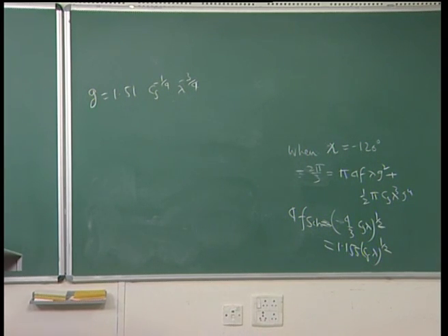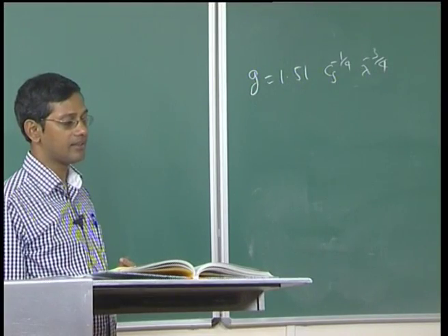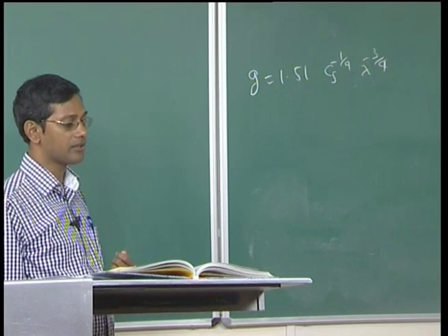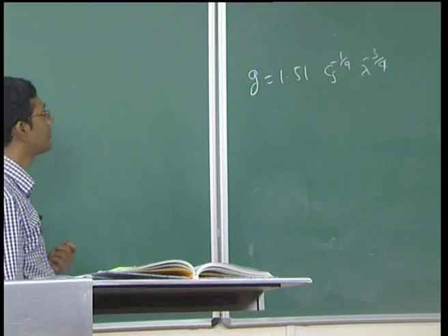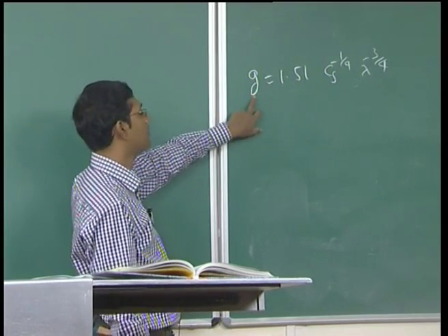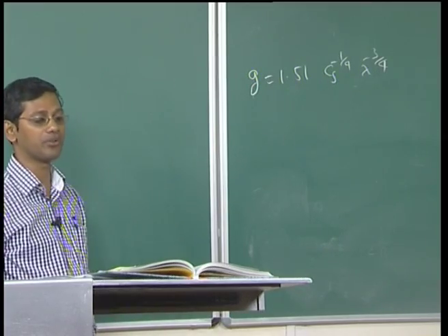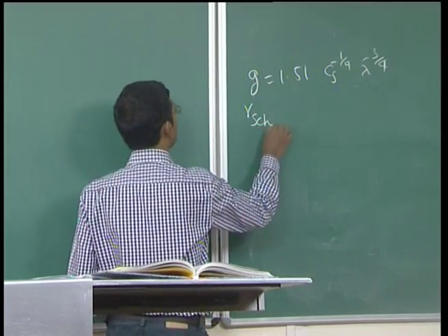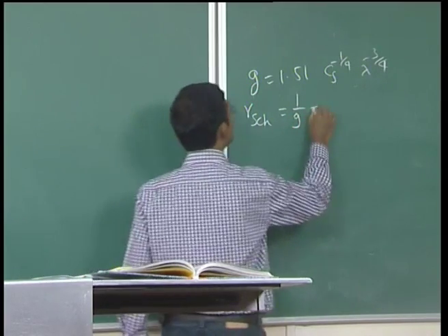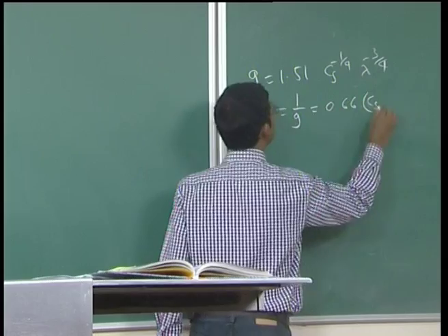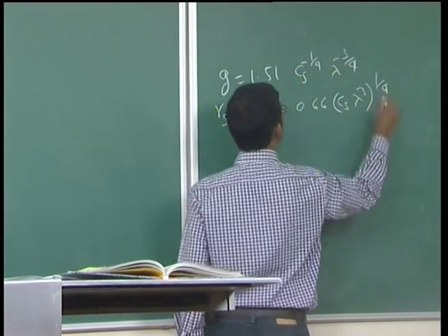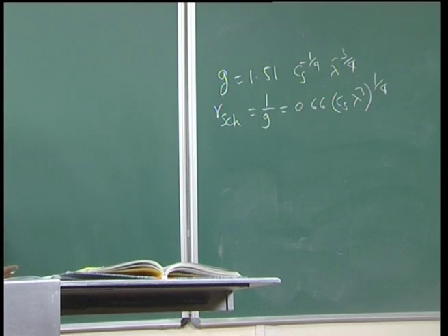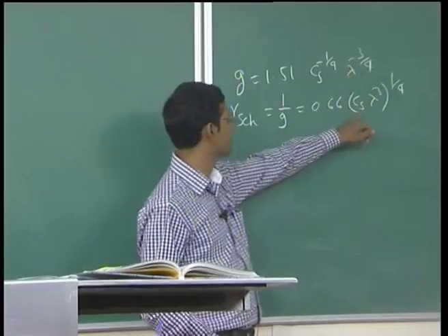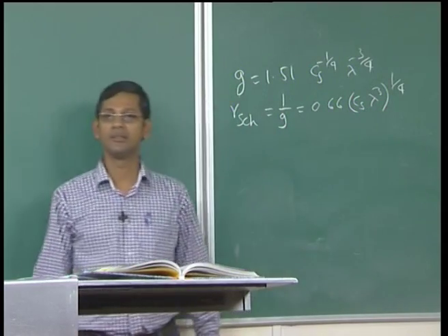And this crossover is very important in the sense that at the Scherzer defocus, corresponding to this value of g, it will give us the resolution limit of the microscope. And this resolution limit can be obtained by taking the inverse of this, which is equal to 0.66 Cs lambda cubed to the power 1 by 4. So, this gives us the optimum resolution limit, or actually the resolution limit, for any transmission electron microscope. By knowing Cs of the objective lens and lambda, we can get that.